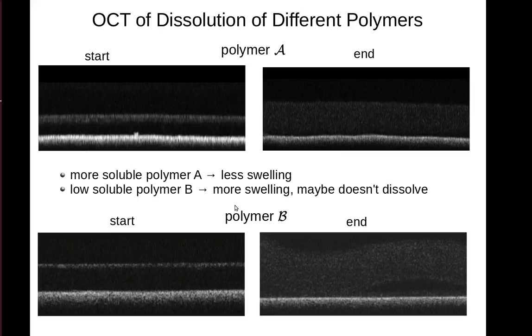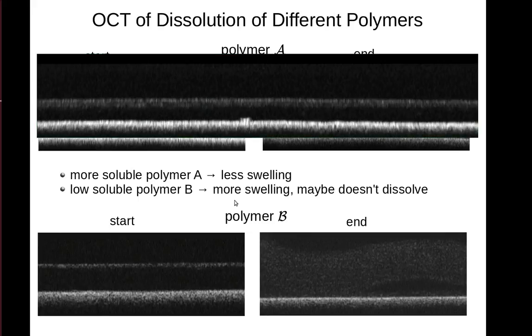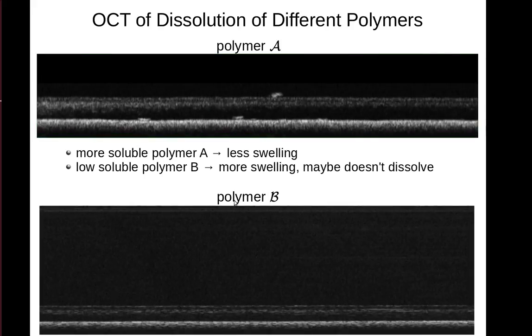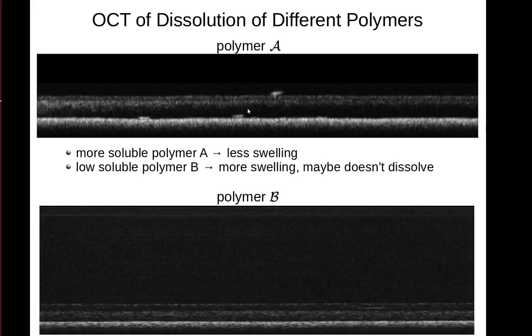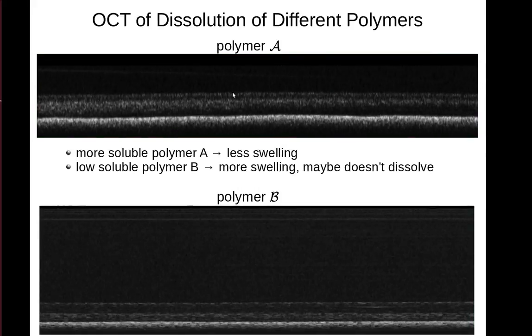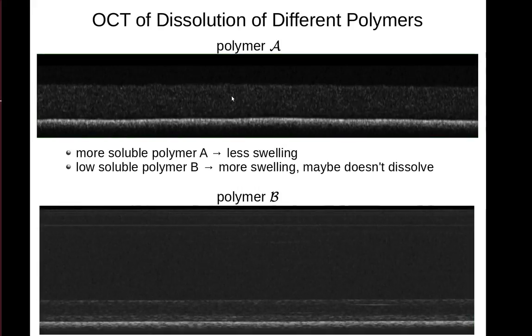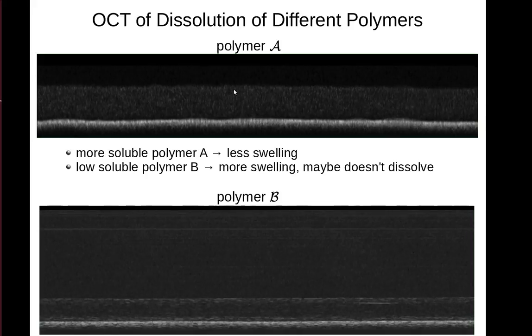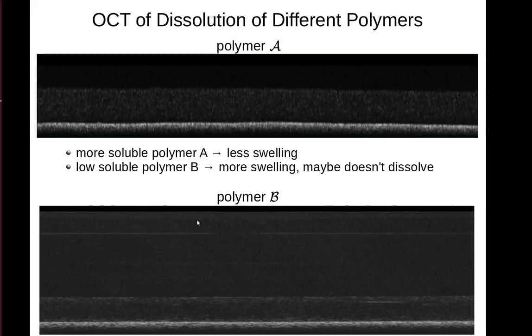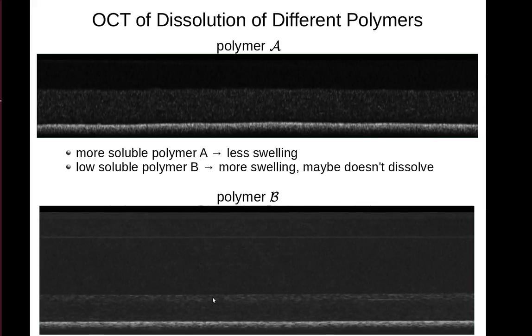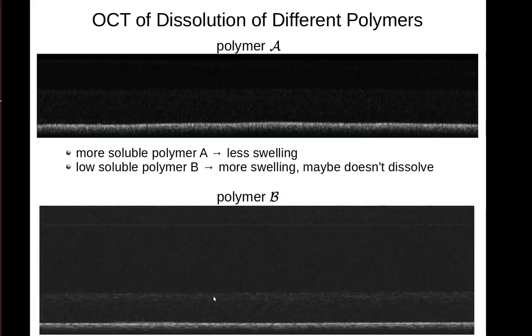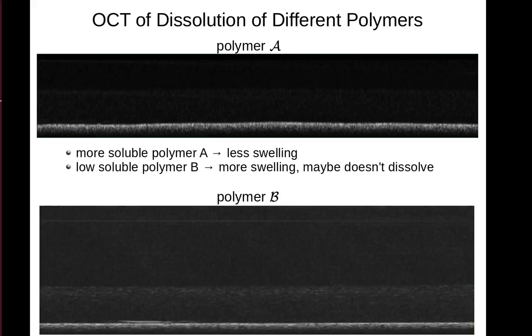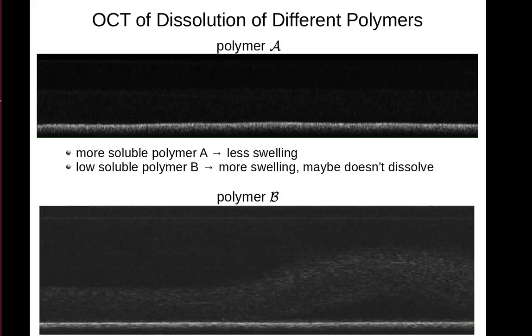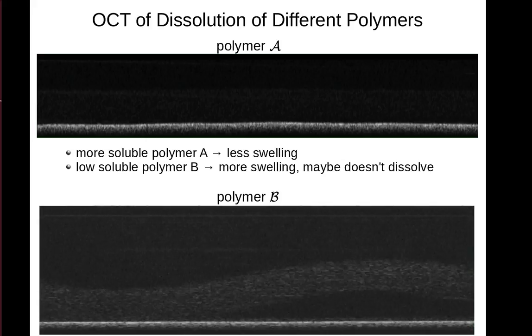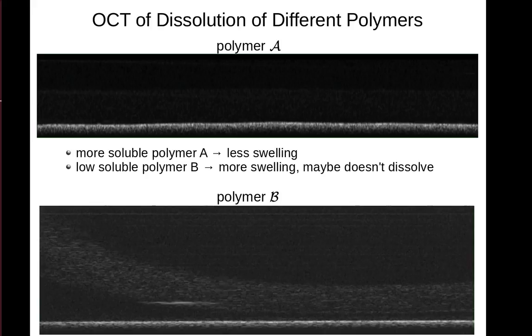So let's observe what happens dynamically over the time of this dissolution. The top again shows what we've seen before. Polymer A starts with just a regular film and begins to swell. It swells probably by about 50%, and it'll slowly dissolve. Polymer B, on the other hand, swells for considerably longer time and a larger amount, almost doubling its size. Then a very interesting thing occurs before the experiment is done. The polymer actually delaminates from the microscope slide.